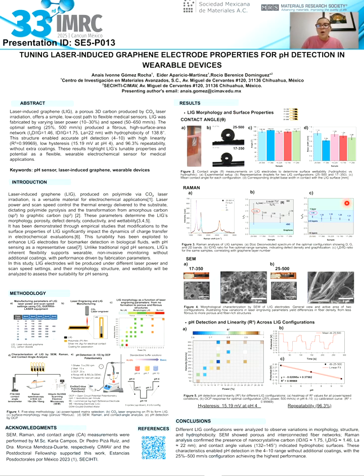Figure 2 illustrates how the pH buffer droplet interacts with the active LIG area. To evaluate the behavior, contact angle measurements were conducted, allowing the distinction between more fibrous and less fibrous surfaces. Figure 2b shows two representative examples, a more fibrous and a less fibrous one. The full analysis for the 5 configurations, figures 2c and 2d, reveals that all present a contact angle above 90 degrees, indicating hydrophobic behavior, with a similar trend observed in the droplet base width. This result suggests that morphology plays a key role in the surface ability to repel or retain liquids.